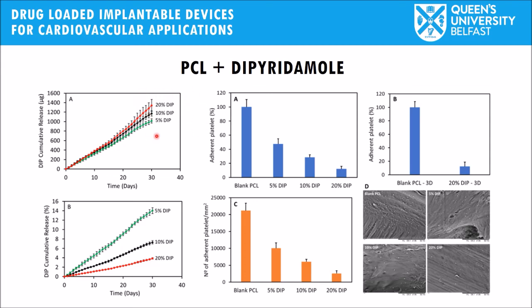And what we observed is that the materials containing 20% dipyridamole showed a clear reduction in platelet adherence to the material. Considering that the amount of dipyridamole released from these materials is almost the same, we can conclude that, in order to prevent the attachment of platelets, the amount of dipyridamole on the surface of the material is more important than the one that is released.